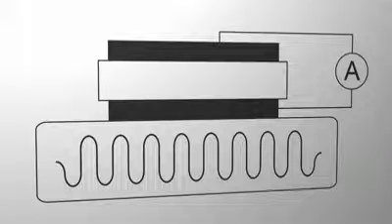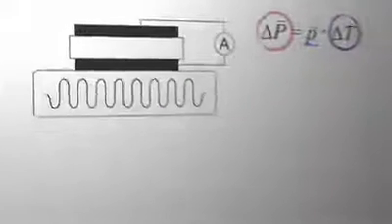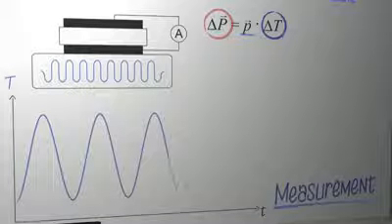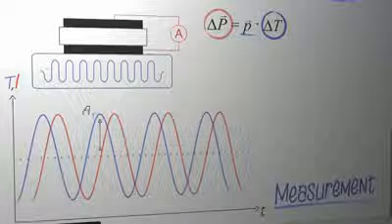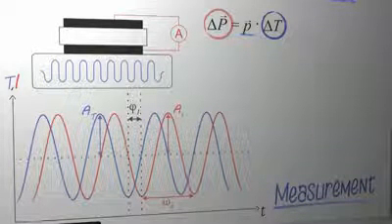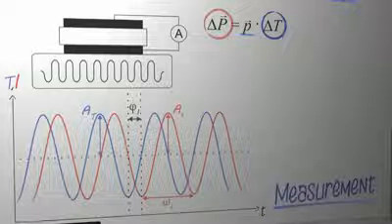Typical measurement techniques for pyroelectric properties, like the Byer-Roundy method, are unsuitable for characterizing the MFP phase because they cannot distinguish between pyroelectric and thermally stimulated signals originating from thermal detrapping of charge carriers. We therefore chose the Sharp-Garn method, which is based on a sinusoidal temperature excitation, by simultaneously measuring the current response of the material and determining temperature amplitude, current amplitude, angular frequency, and phase shift between temperature and current. A non-pyroelectric material shows only thermally stimulated currents which are in phase with the temperature excitation. If the material becomes pyroelectric, a pyroelectric current out of phase arises.